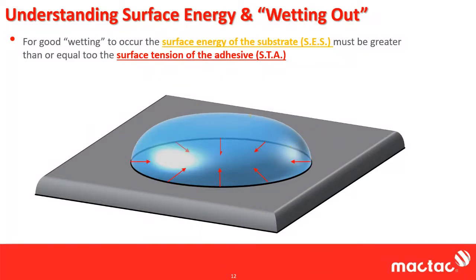which is again represented in the red. So as the surface is trying to pull that adhesive and get it to wet out and go along the surface of the material, you have the surface tension trying to maintain the shape of the droplet and pull the liquid back. And it's this balance between the two which really determines how well an adhesive bonds. This is really the interaction between surface energy and surface tension.